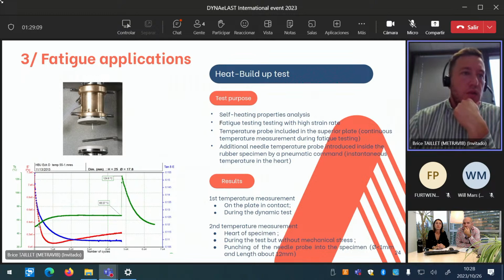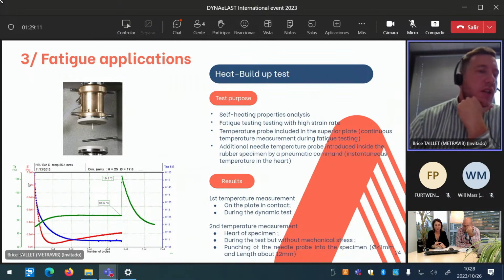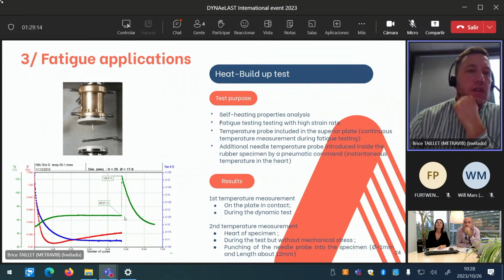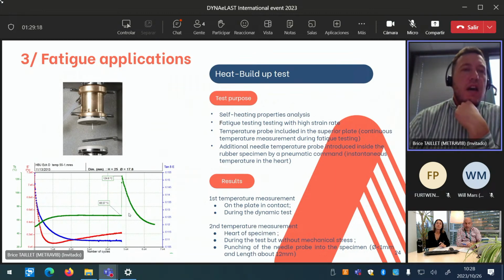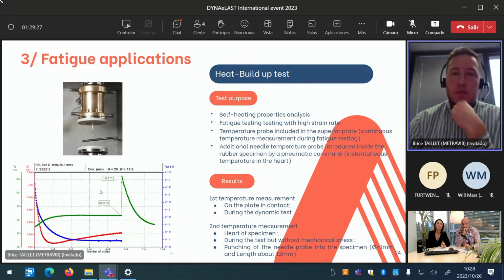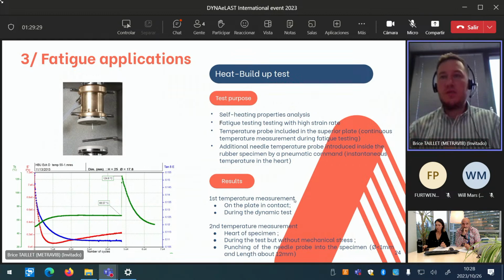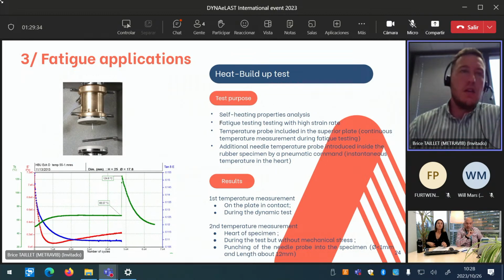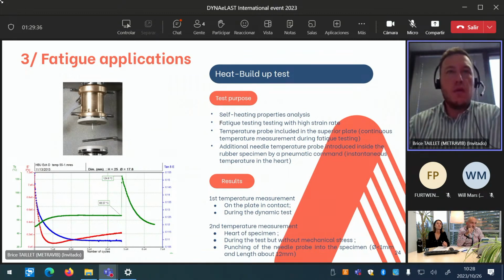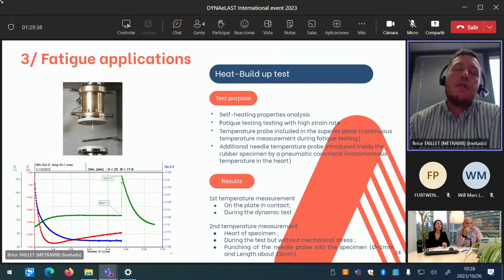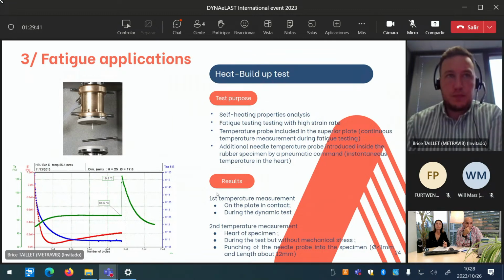That's the evolution in green that we can see on the illustration. We finish the fatigue test at 66 degrees, and after pushing the needle into the specimen, the internal temperature is above 125 degrees. Okay, it's just to characterize the self-heating properties of your materials. Once again, really focused on rubber, of course, and really focused on the tire industry.